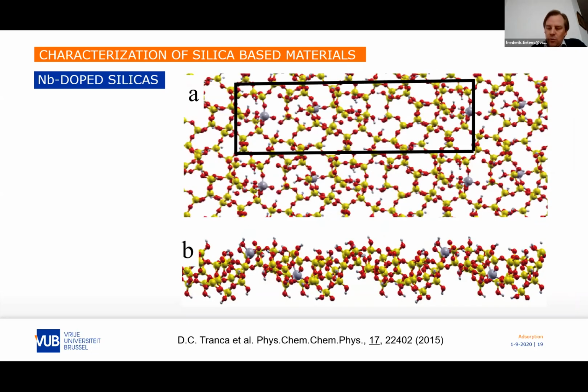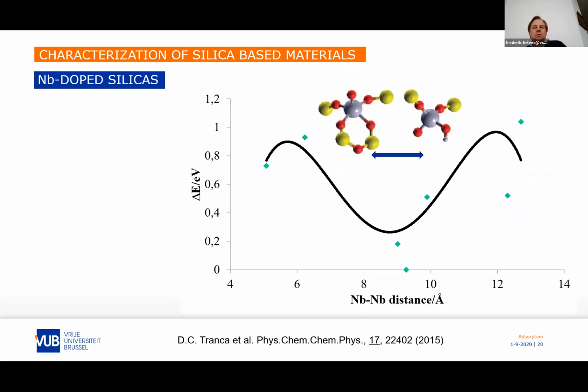And for that we built a double model, introducing 2 sites at the same surface, and displacing, moving one niobium relative to the other one, on our amorphous silica surface. And we studied the interaction between them, and we found out, in fact, that there was a minimum at a certain distance. And this corresponds to the size of our unit cell, which means that the two niobiums want to be as far as possible from each other.